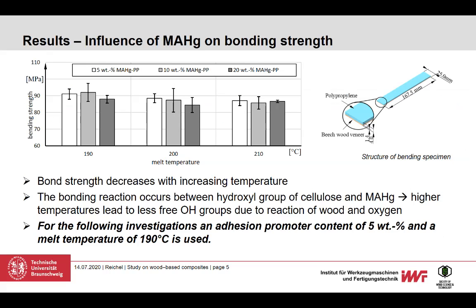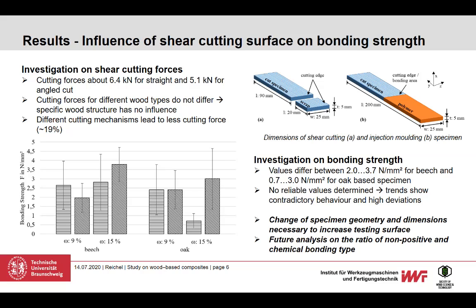So the first one, as you can see, are the results of the influence of the bonding agent, which were determined by using 3-point bending specimens. The results showed that increasing temperature of the polymer melt leads to a decrease in the bending strength, which is the result of the chemical reaction between free OH groups and the maleic anhydride, because higher temperatures lead to fewer free OH groups and therefore less bonding. Our optimal parameters we found were 190 degrees Celsius and 5% weight ratio, which we used in the next experimental step, which was the investigation of the bonding strength of the combined hybrid prototype.